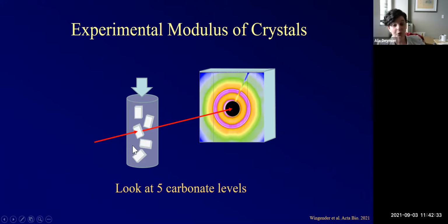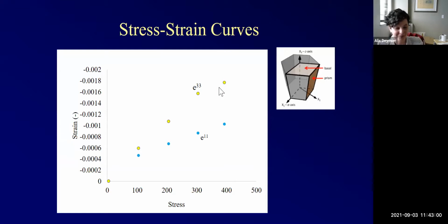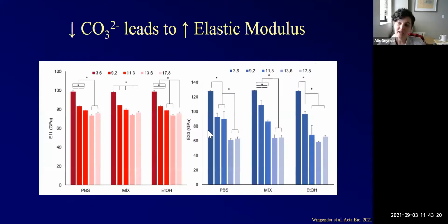We're then sending X-rays through the crystals themselves and getting an X-ray diffraction pattern. Now this X-ray diffraction pattern, just like you would do in the lab, gives you information about the lattice spacing. Now, because I can see what the lattice spacing is at each different stress or at each different pressure, all of a sudden I have a strain measurement. So by doing this experiment on these crystals with different levels of carbonate, what I can get is a stress-strain diagram. And because I can get it for the 002 and the 310, I can actually get the strain for both the C-axis and the A-axis. From this bunch of math, you can check out the paper, we can get essentially the elastic modulus along the C-axis and the A-axis, because these crystals are anisotropic, as a function of carbonate content.